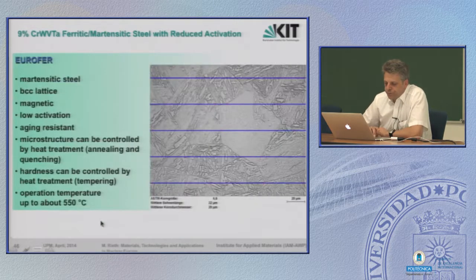Now, let's come to Eurofer. As said, this is a martensitic steel. You see it here in this typical martensitic structure. You can easily see the former austenite grains. It's a BCC lattice. Unfortunately, it's also magnetic, which has an effect on the whole plasma physics inside the reactor if you use it, but it's low activation and it is aging resistant. You can keep it at temperatures for years and it doesn't change the chemical composition. There is no formation of second phases. The microstructure here can be easily controlled by heat treatment.